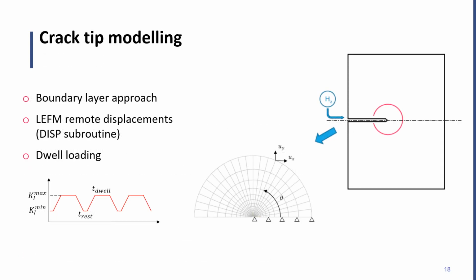To study hydrogen accumulation and hydride formation, we consider the typical boundary layer approach, in which a crack with a small radius is loaded with remote displacements. These displacements are proportional to a stress intensity factor, and they follow the theory of linear elastic fracture mechanics. We use a user displacement subroutine in Abaqus to make this loading automatic, and we reproduce a cyclic dwell distribution for the stress intensity factor.